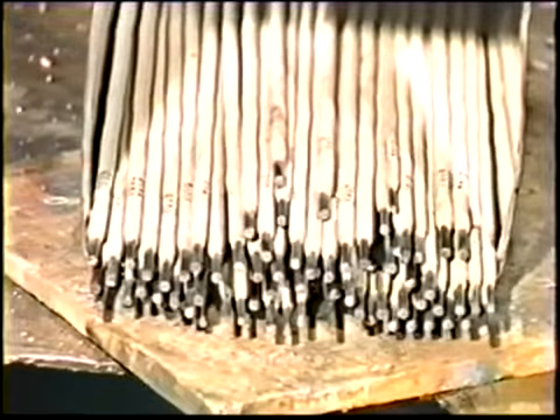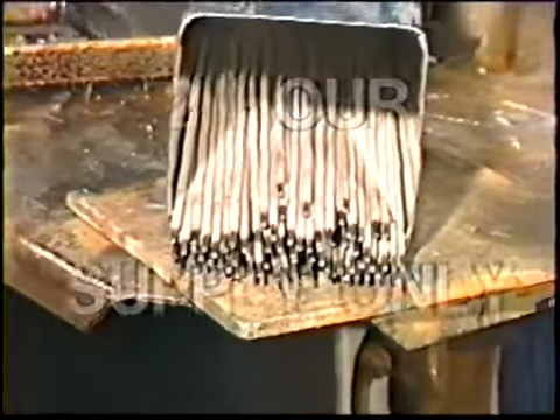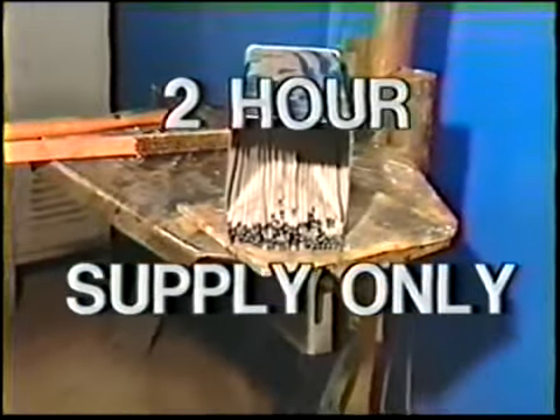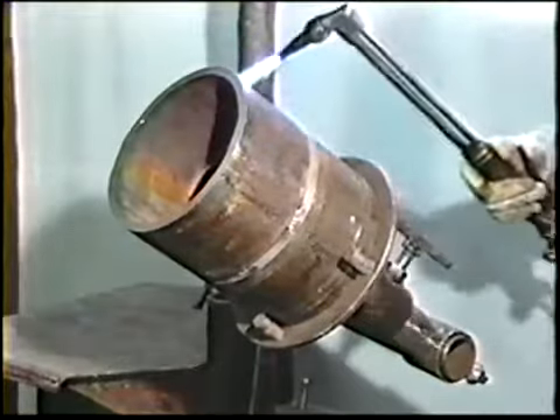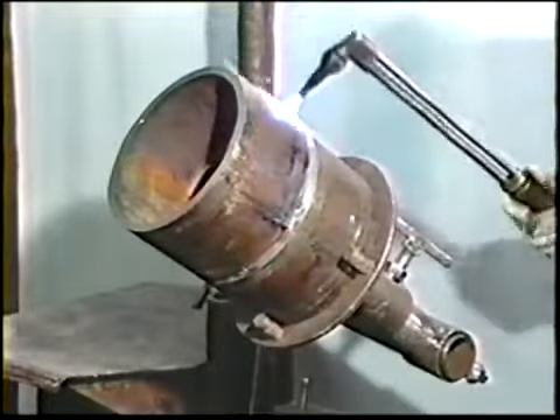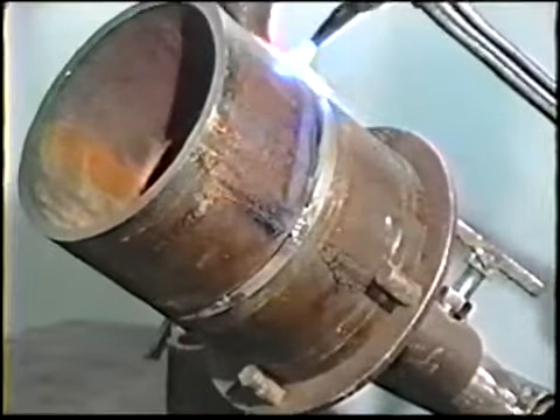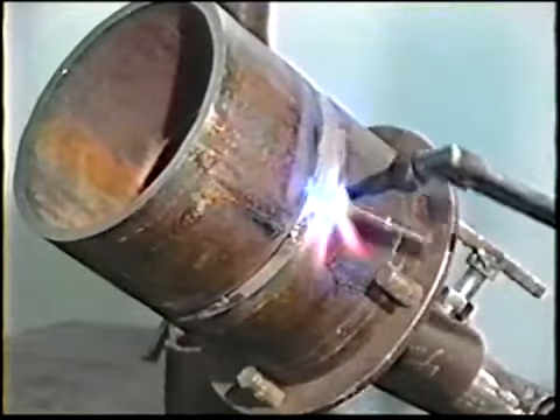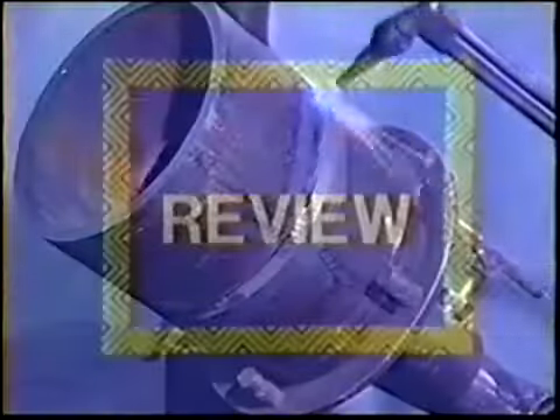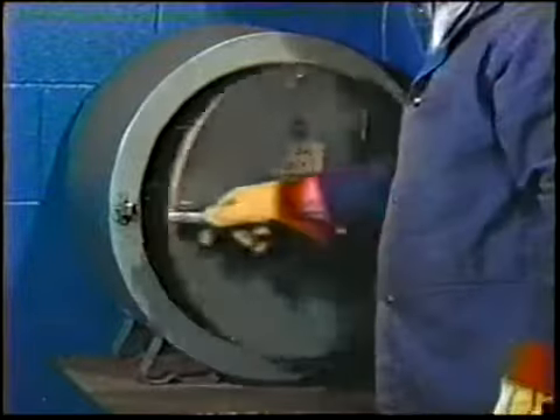As a basic precaution against moisture and humidity damage, do not remove more than a 2-hour supply of electrodes from a sealed container. In addition, if the joint is damp, apply heat with a torch to completely dry the area of the weld. Do not weld on surfaces covered with oil, water, dirt, paint, and so forth. In review, the main precautions to remember for using low hydrogen electrodes are: maintain a short arc length, never weld with a whipping motion or in a downhill direction with multiple pass joints. Always clean the slag completely off after each pass is deposited, and keep the electrodes dry.